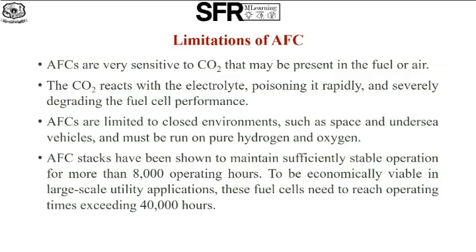AFCs are very sensitive to carbon dioxide that may be present in the fuel or air. The CO2 reacts with the electrolyte, poisoning it rapidly and severely degrading the fuel cell performance. AFCs are limited to closed environments such as space and undersea vehicles and must be run on pure hydrogen and oxygen. AFC stacks have been shown to maintain sufficiently stable operation for more than 8,000 operating hours. To be economically viable in large scale utility applications, these fuel cells need to reach operating time exceeding 40,000 hours.